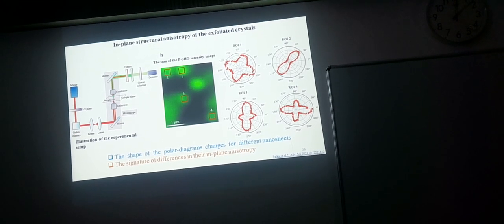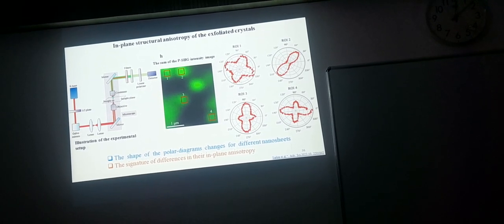As I mentioned, this material is anisotropic, so maybe I should go to the next slide. For anisotropic materials, there are various ways to prove that they have optical or electronic anisotropy. One of the important tools is anisotropic Raman spectroscopy, or absorption or photoemission spectroscopy. But one problem here is the flake size is very small, and for optical systems we have a certain optical limitation, because most laser beams are more than 500 nanometers, or close to a 1 micrometer spot. If you focus with this 1 micrometer spot and your material is smaller than that and oriented in different directions, you will collect the signal from all the differently oriented samples, and it's quite hard to understand the anisotropy or the crystal orientation dependent optical properties.